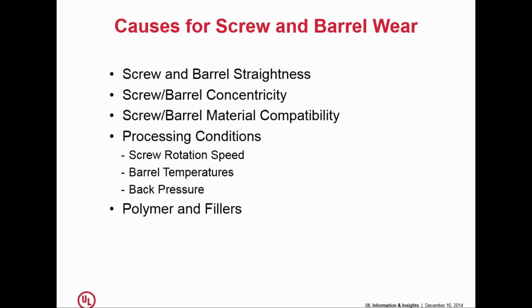I've seen amazing amounts of screw wear in machines running nothing but high-density polyethylene, simply because the material is not melting at the point where it should be melting, and so you're getting an awful lot of pressure being developed between the screw and the barrel wall with material that's still in the solid state when it should no longer be in the solid state. Any of you who've been out there long enough to really experience a wide range of molding processes has seen this happen, so you know this occurs.